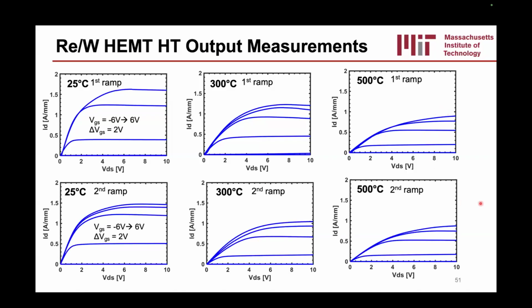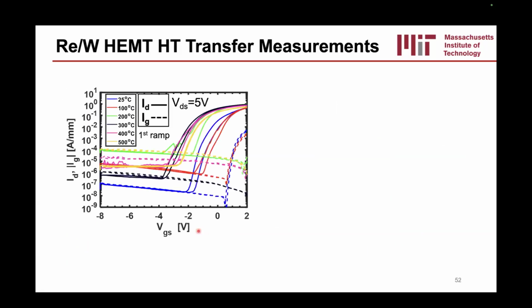And then we can do a second round where we cool down the device and then do the exact same thing. And we can see basically more or less the same characteristics in the second round, at least from the output characteristic point of view. What's interesting is if we look at the transfer characteristics, they change significantly. So in the first round, it's a little bit all over the place.